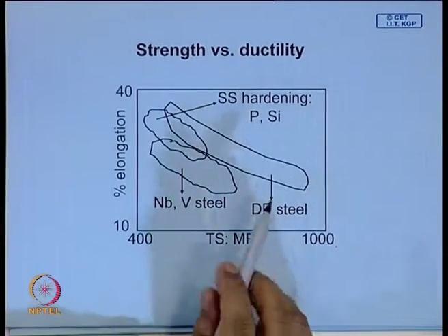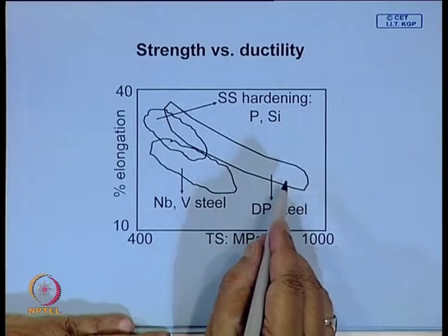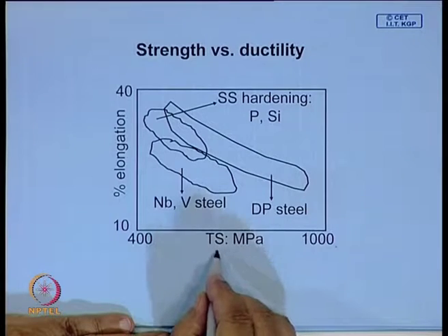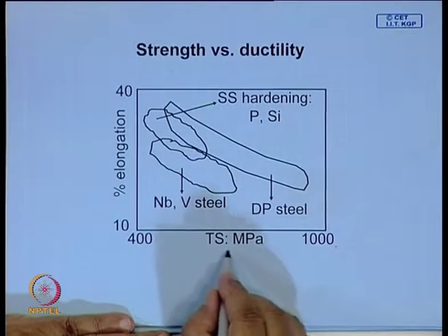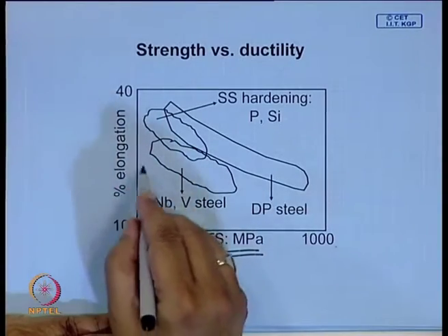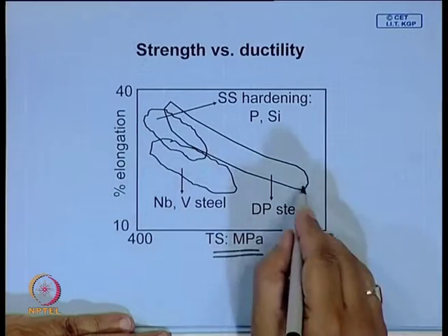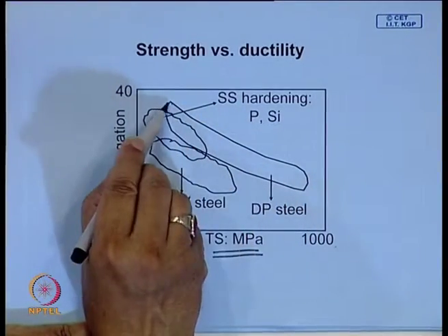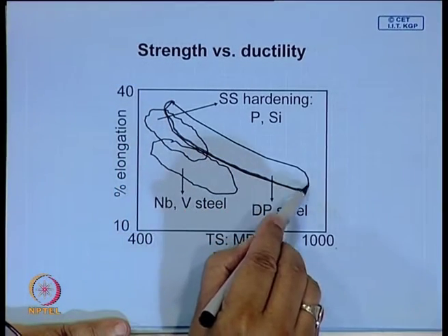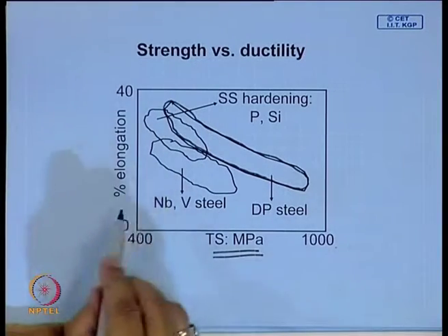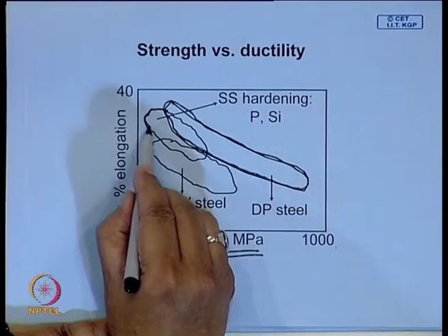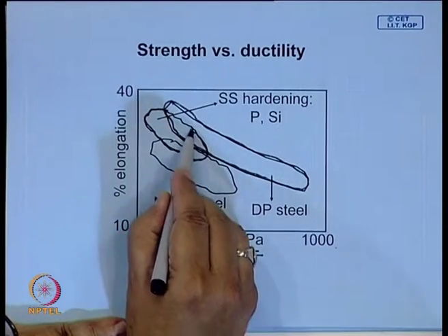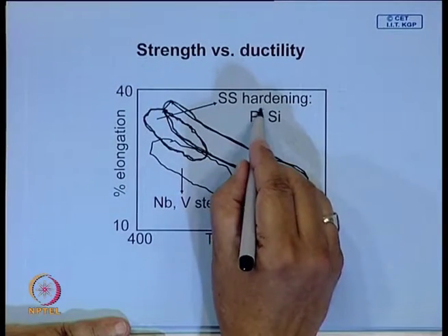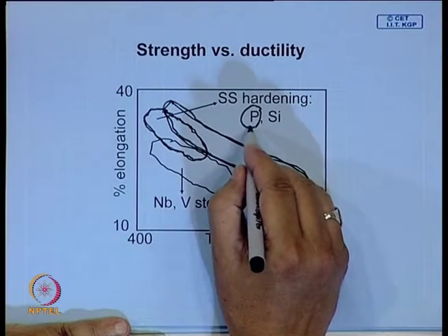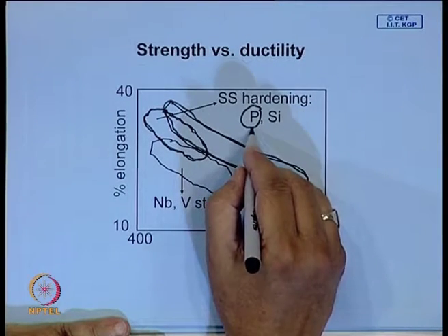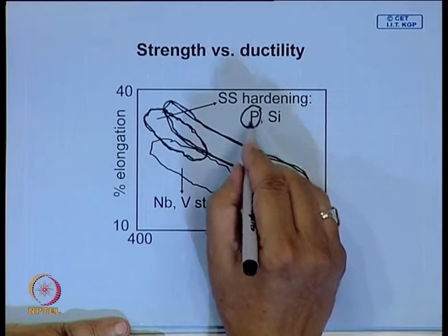Now, dual phase steel, what is most attractive is that it gives a better combination of strength and ductility, because in many applications strength may not be enough, it must have a very high degree of ductility. Look at this, this is the region of the dual phase steel, and how does it compare with conventional steel? In conventional steel the main strengthening mechanism is solid solution strengthening, and phosphorus, a little phosphorus, can significantly increase the strength, but it segregates, it makes the steel brittle. So, these are the problems.